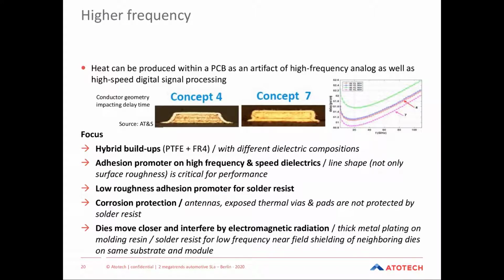When not directly plated onto the solder resist, plated shielding layers also become more important, especially for components and modules. Dies and chips move closer and interfere by electromagnetic radiation. At frequencies below 100 megahertz, sputtering and ink spraying will not work anymore. They are much too thin to be effective, and uniformity for three-dimensional structures is not given, especially the sidewalls of components. So thick metal plating is needed. This can be done by electroplating. So electroplated copper and electroplated soft magnetic layers will help for shielding. And this combination is proven to effectively shield neighboring dies on the same substrate or module.